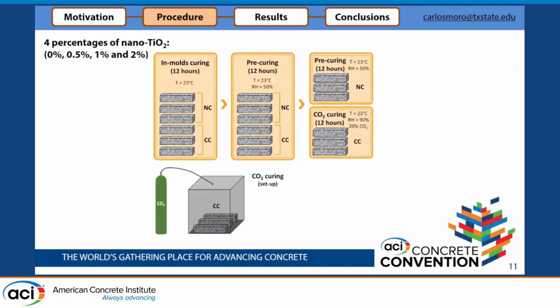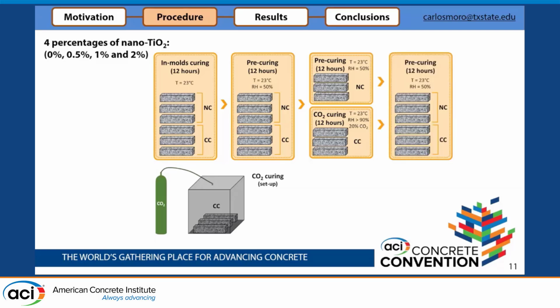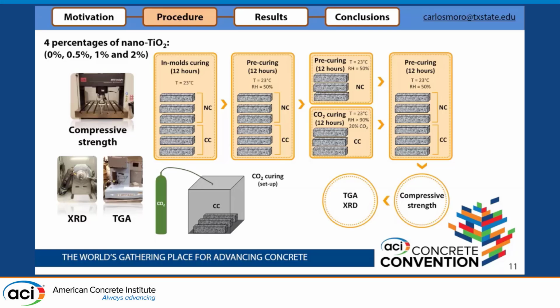Then we had 2 different groups, basically. I put pre-curing, but it's basically conventional curing, where the samples stay in the same curing room. And then we put a group in the CO2 curing chamber with a 20% CO2 concentration for 12 hours. And then we moved the CO2-cured samples again to the same chamber, and we tested compressive strength and then TGA and XRD to explore the microstructure further.